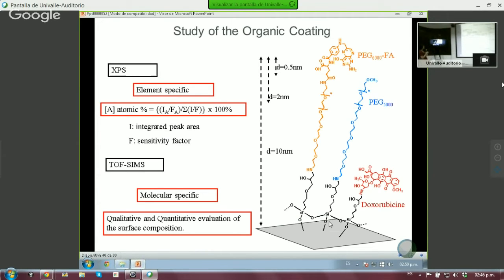So in this case, what we wanted to do is look at the surface and make sure that none of these drugs came to the surface, and that what's on the surface is what we believe it is. So we actually used two techniques. One is XPS, and I think you have it here. XPS allows you to look at surfaces. It's element specific, and you can in a way tell numerically how much you have on the surface. But the problem with it is that it can only see the surface up to 10 nanometers from the surface, and you can squeeze it to 2 nanometers.